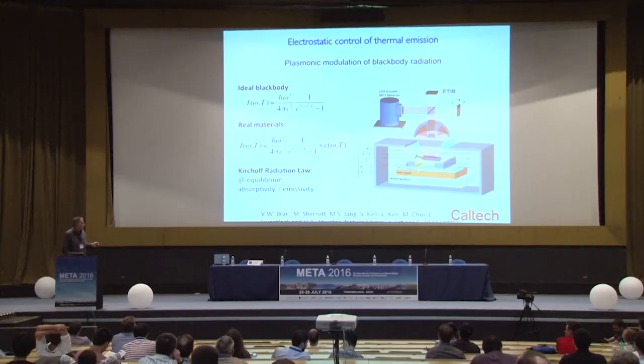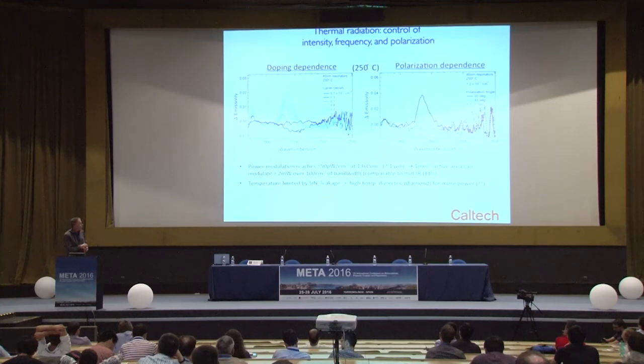So speaking of reciprocity, in these structures, unlike the nice, beautiful structures that Andreas showed, these are indeed reciprocal structures. So we expect by reciprocity inherent in the Kirchhoff radiation law that the absorptivity of layers of graphene should be proportional to the emissivity. And indeed, that means that we can tune by essentially now heating up and allowing these structures to become emitters. We can electronically tune the emission of graphene. And we've shown recently that we can see this, that we see a tunable emittance, electronically tunable emittance.